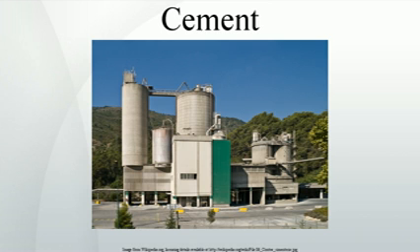This is primarily due to the very high temperatures of the kiln gases, 2000 °C in the combustion gas from the main burners and 1100 °C in the gas from the burners in the pre-calciner. The gas residence time at high temperature in the rotary kiln is of the order of 5 to 10 seconds and in the pre-calciner more than 3 seconds.